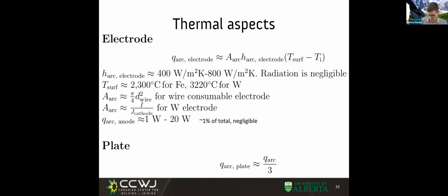So in this last slide before we stop, I want to address the part that is the contribution of the arc to melting. So we talked about the voltage fall in the anode and the voltage fall in the cathode. And the arc gives some amount of energy to the plate and to the electrode. The energy to the electrode, right? We're going to use this formula that is similar to the ones we use in heat transfer. Area times convection coefficient times a delta T, right? And the convection coefficient for heat from the arc into the electrode is more or less 400 watts per meter squared Kelvin. It's high for being a gas, but it's quite reasonable. This lets us calculate the effect of convection into the electrode.